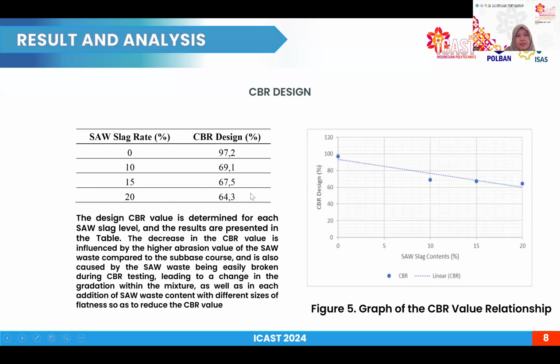This is the result of the CBR design. The design CBR value is determined for each SAW slag level, and the results are presented in the table. The decrease in the CBR value is influenced by the higher abrasion value of the SAW slag compared to the sub-base course, and is also caused by this SAW slag being easily broken during CBR testing, leading to a change in the gradation within the mixture, as well as the addition of SAW slag content with different sizes and flatness, so as to reduce the CBR value.